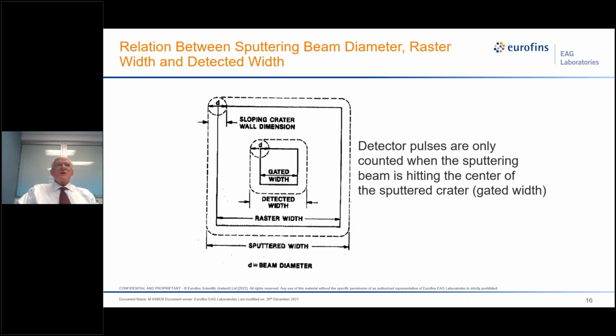Now, the primary beam is very important, and people ask, how small an area can you analyze? Well, it depends on how small the primary beam is. We can have beams as small as 2 microns or as big as 50 to 100 microns. But we raster it in this square pattern. The size of the beam is indicated by this circle here. This area here is gated: detector pulses are only counted when the sputtering beam is hitting this center part of the crater. Because this is going to be the flat bottom of the crater, and we don't want to see things on these crater walls because that's at a different depth. But it's difficult to shrink the sputtered area down very close to the gated area, because then the sloping crater wall will start to overlap on the gated area.